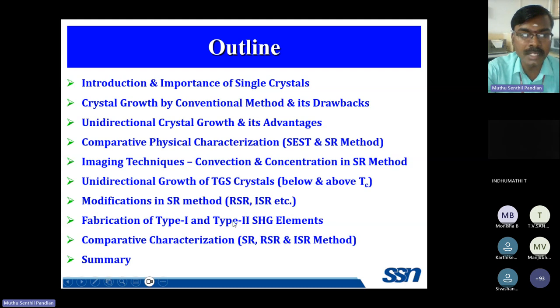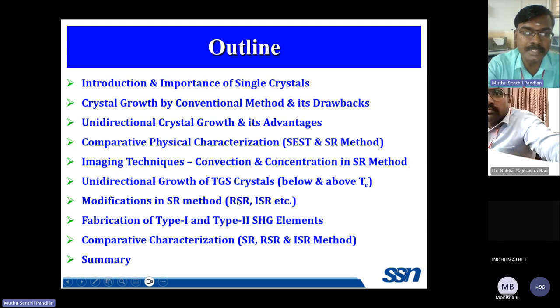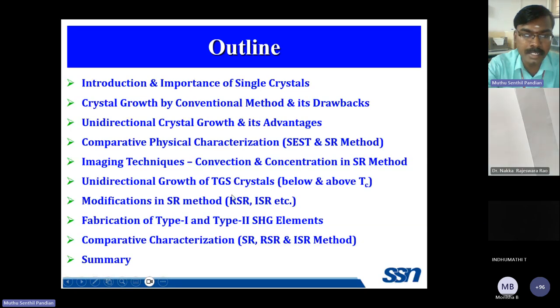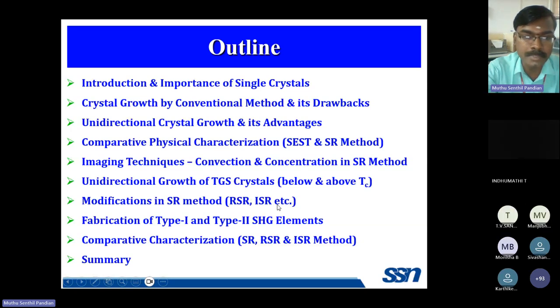And this is the special material, TGS, triglycine sulfate, a very good ferroelectric single crystal. We have grown the crystal at its ferroelectric and paraelectric phases, and we have compared the physical properties and crystalline perfection to see which phase grown crystal is more suitable for ferroelectric infrared detector application. And in order to get high purity, higher crystalline perfection and higher physical properties, we have made a lot of modifications in this conventional SR method: RSR and ISR, meaning rotational Sankaranarayan Ramasamy method and immersible Sankaranarayan Ramasamy method.